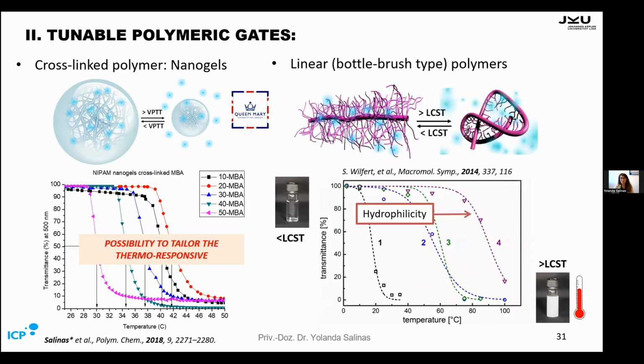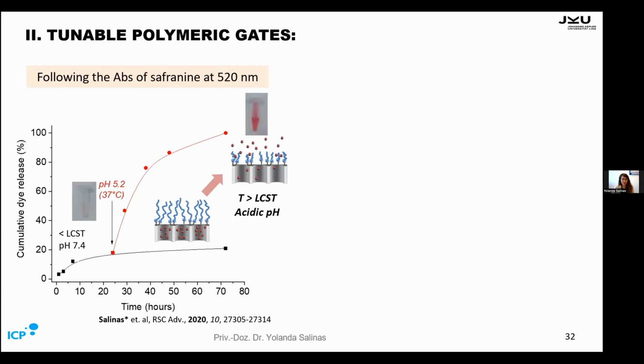So based on that typical nanogel, we used polymers like polyphosphazenes to create a more bottle brush type, which could be collapsed as well and let the release happen. Here I am showing you that there is a possibility to increase or decrease the hydrophilicity of this material just by changing the organic sides. So we used this polymer and attached it to the silica particles, and we could see that below the LCST, which is the thermoresponsiveness of this polymer, there was almost no release happening, as we can see here. But when the pH was below neutral pH, we could see a very large increase in the release of the drug.